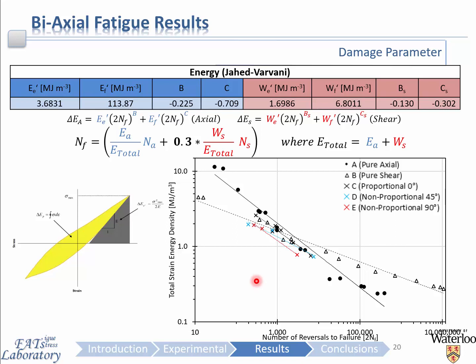Of those, a smaller subset exists which work well for materials with asymmetric and anisotropic behavior. Using energy as the basis for a damage parameter is a robust method for magnesium alloys, since it's a scalar quantity that is invariant of direction, so it's quite convenient too.